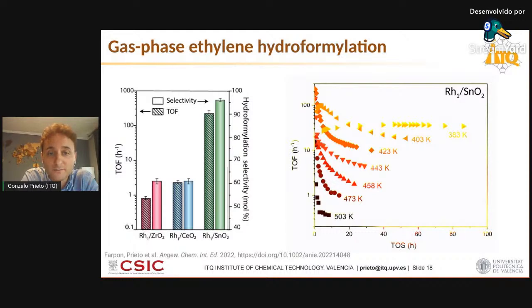That's the full bars. But we were very delighted to see that under the very same conditions, rhodium single atoms stabilized on tin oxide showed orders of magnitude, note the logarithmic scale in the y-axis, two orders of magnitude higher reaction rate per unit center than those supported on zirconia and ceria. Very interestingly, together with selectivities to hydroformylation above 95% at this temperature, this is data at 150 degrees C, but we could improve that selectivity to essentially 98-99% by operating at a slightly milder temperature. So we were very positively surprised on the one side and intrigued on the other by the performance of this single atom catalyst. And this is why we decided to first of all do a temperature screening to see how this catalyst behaves at different operation temperatures.